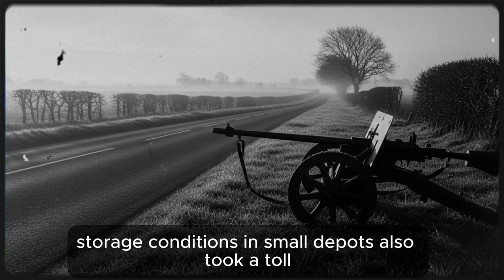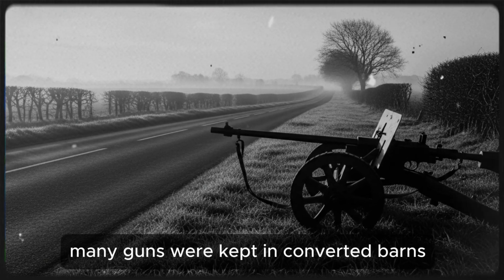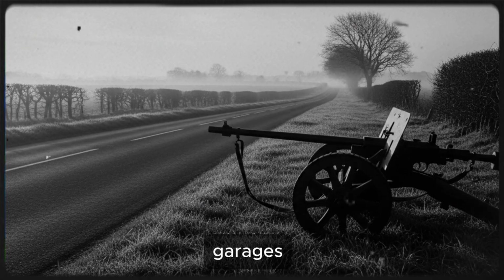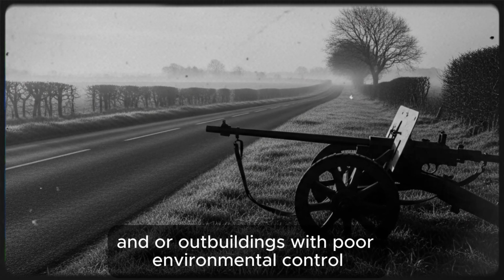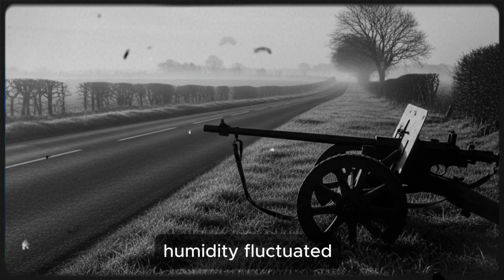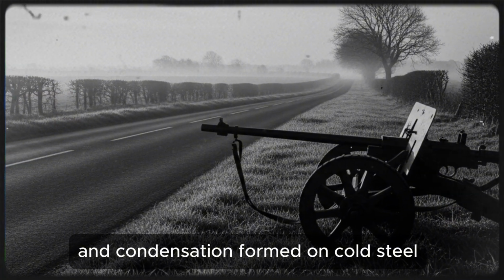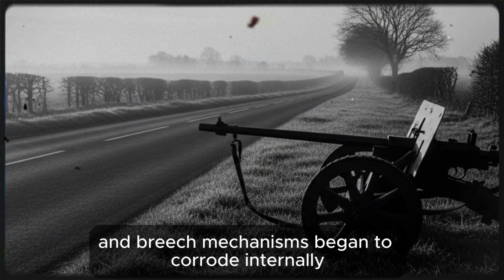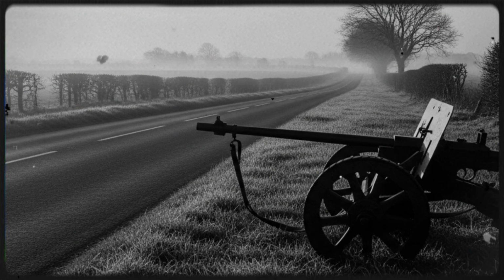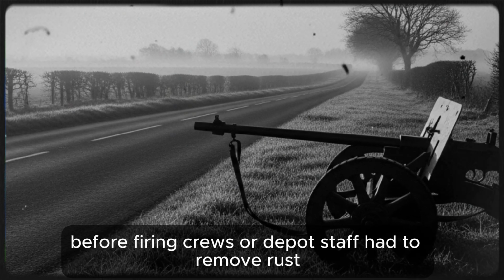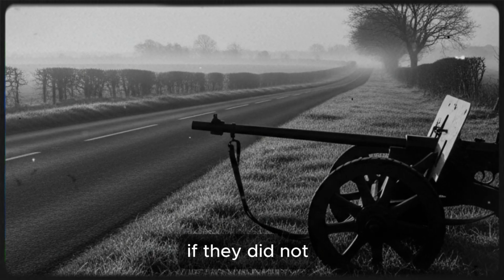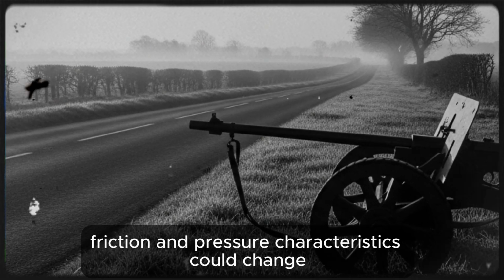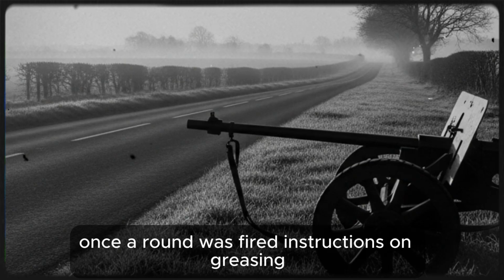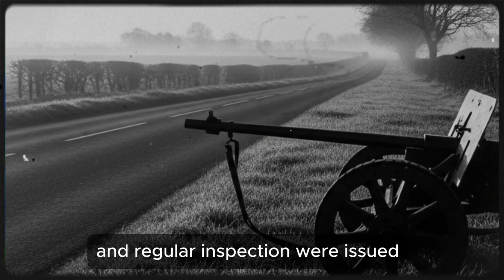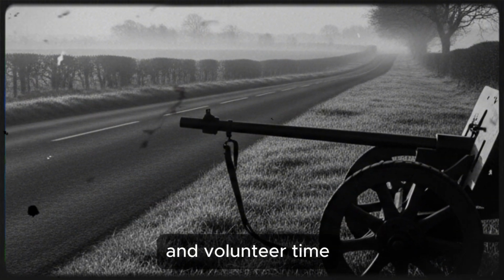Storage conditions in small depots also took a toll. Many guns were kept in converted barns, garages, and outbuildings with poor environmental control. Humidity fluctuated, and condensation formed on cold steel. Barrels and breech mechanisms began to corrode internally. Before firing, crews or depot staff had to remove rust. If they did not, friction and pressure characteristics could change once a round was fired. Instructions on greasing and regular inspection were issued. Compliance depended on local leadership and volunteer time.